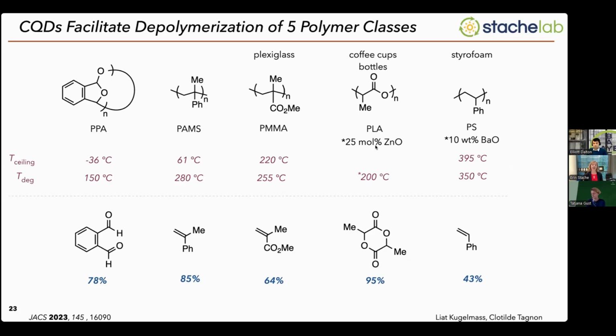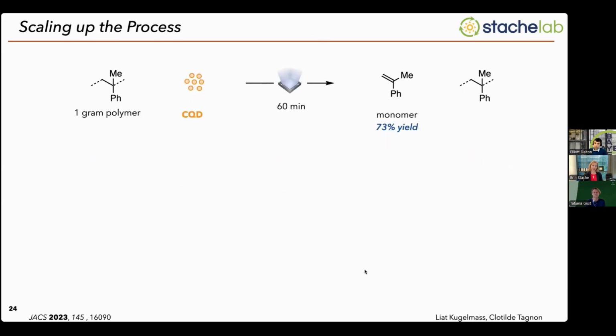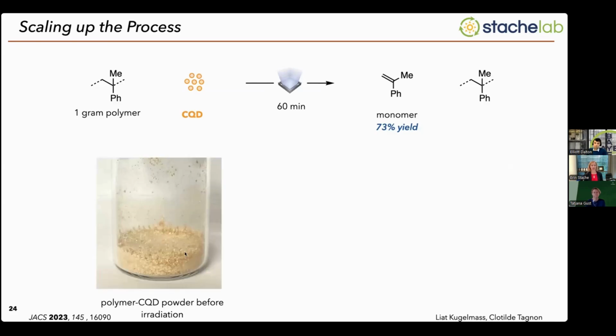So this worked, and it worked with an exogenous catalyst as well. We're using two different forms of photothermal catalysis in this case. And then, of course, polystyrene, the polymer that we're really trying to depolymerize. We took commercial polystyrene foam, added barium oxide, and induced depolymerization to about 43% yield using these carbon quantum dots. We were able to scale this up to 1 gram.